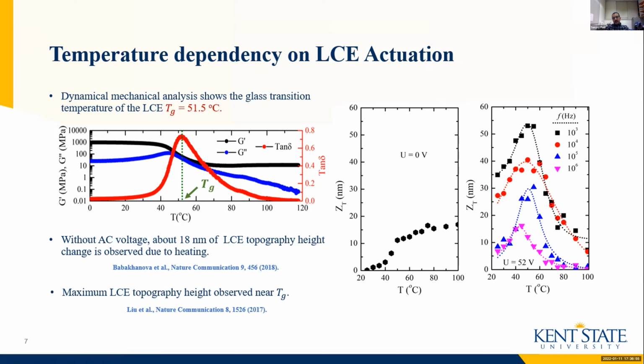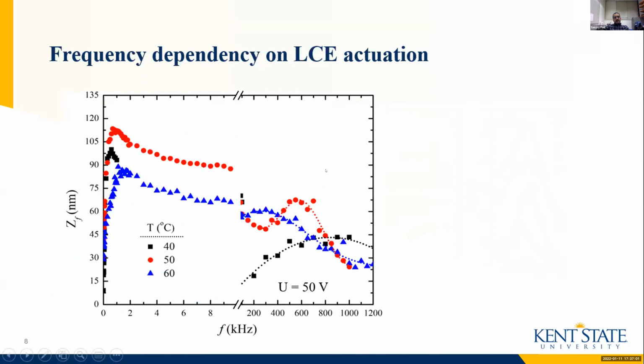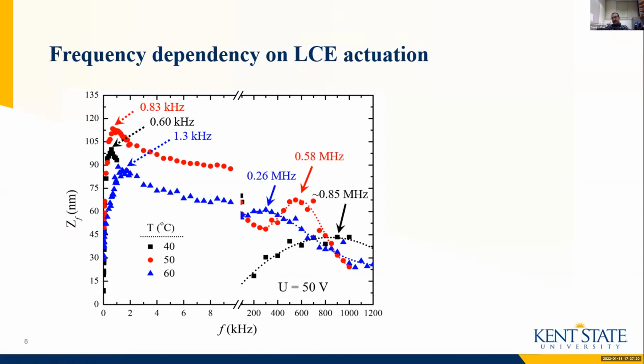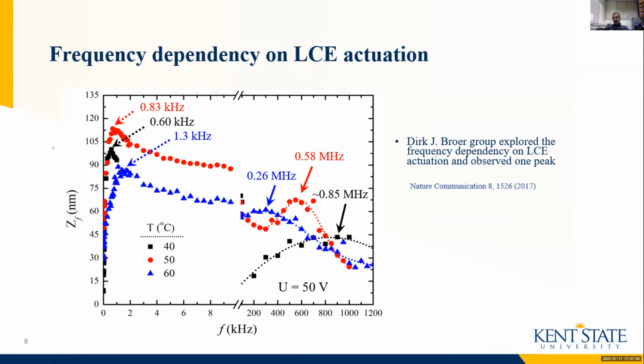To understand this, we did further analysis of the frequency response of the AC electric field. So here is the plot. We see the topography height changes in the frequency range from 10 hertz to 1 megahertz. There is an appearance of peaks in the low frequency regime, below 1 kilohertz, and also the presence of another peak in the high frequency regime. Broer group explored the frequency dependency of LCE actuation and observed one peak above 100 kilohertz. But our result shows that we have another peak below 2 kilohertz in the frequency response.